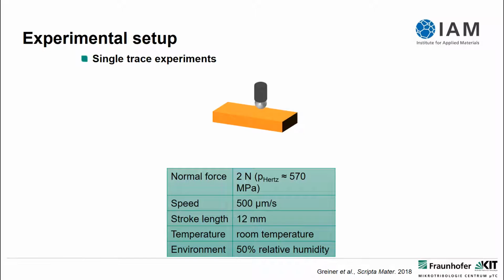We have a sphere with a diameter of 10 millimeters, so 1 centimeter, and a normal force of 2 newtons, which equals a nominal Hertzian pressure of 570 megapascals. And we do this in really slow sliding.